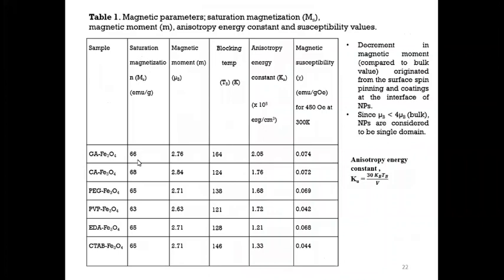So these are the cases. You can see that the saturation magnetizations are above 60 in every case. This is the glutamic acid, this is citric acid, this is PEG, PVP, EDA and CTAB. And this is the magnetic moment. We have calculated the magnetic moment per molecule of iron oxide, and the magnetic moment is coming around the theoretical values, around 2.7 Bohr magneton. And these are the blocking temperatures. The blocking temperatures are well below room temperature, and hence it could be utilized for the hyperthermia.